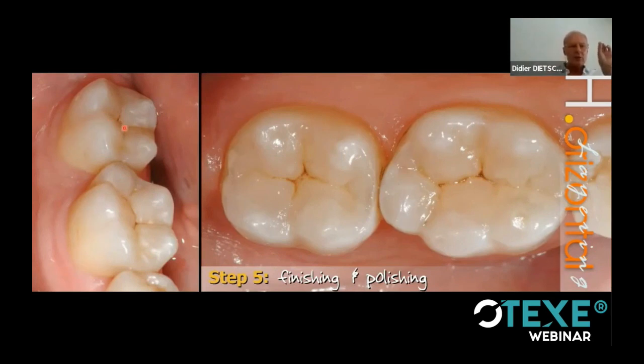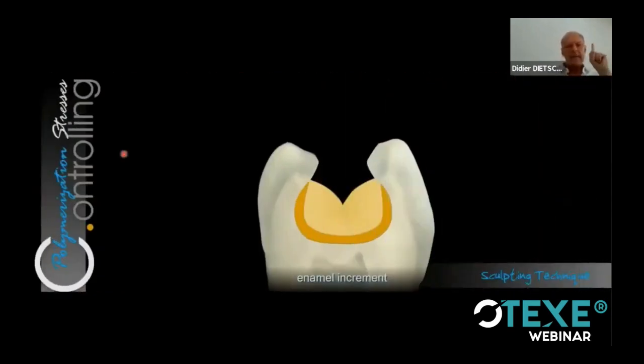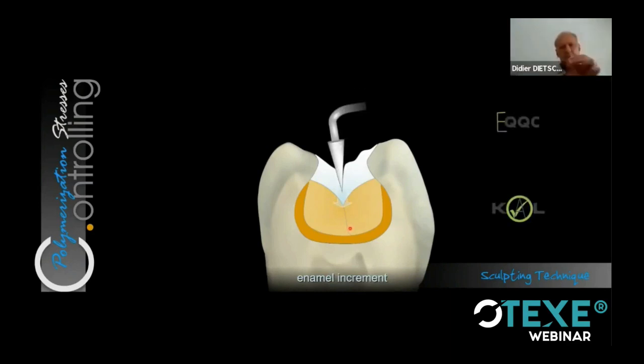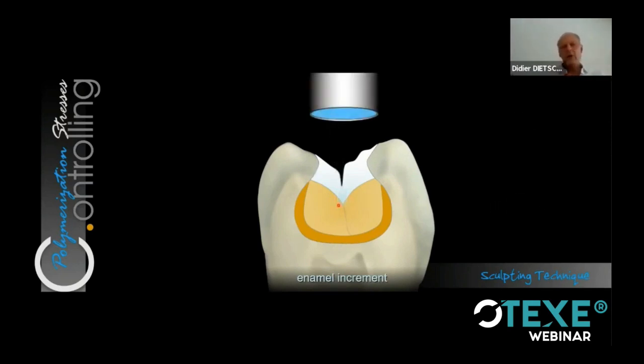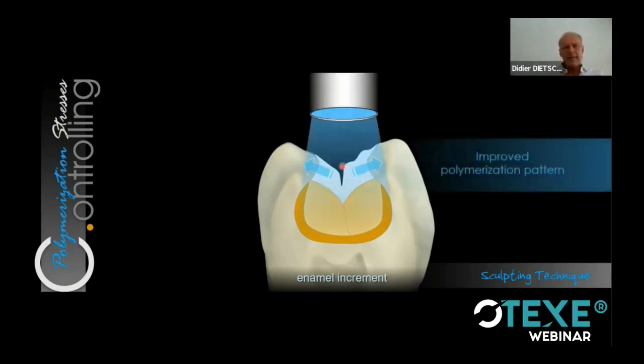Use the remaining tooth anatomy to sculpt your composite in a proper way. Use a good sculpting instrument to make this step. And sculpting is not only a matter of saving time and reducing stress on the margins, but it also has a stress breaking effect. When you go with your instrument deep in the occlusal anatomy, nearly in contact with the underlying dentin, when you light cure the restoration, this will break the stress buildup between the facial and the lingual walls. It's a very effective concept to reduce stresses along the occlusal margins.